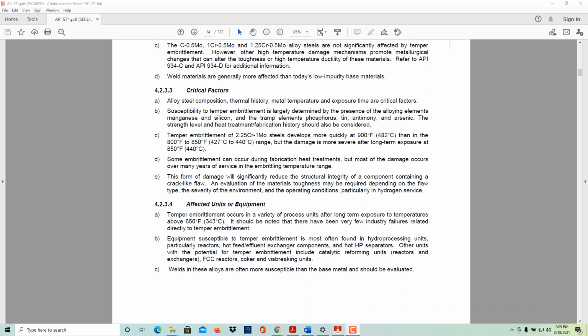Critical factors: alloy steel composition, thermal history, metal temperature, and exposure time are critical factors. Susceptibility to temper embrittlement is largely determined by the presence of the alloying elements manganese and silicon, and the tramp elements phosphorus, tin, antimony, and arsenic. The strength levels and heat treatment fabrication history should also be considered.